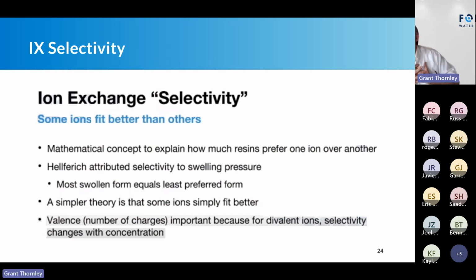It's a mathematical concept to explain how much a resin prefers one ion over another. Again, we have lithium, but we also have lots of other ions in there. So how do we ensure that one ion is going to be selectively removed from another? Helfferich attributed selectivity to the swelling pressure of the beads. That's maybe a difficult concept to wrap your head around, but there is a finesse to that. As the bead loads, it swells and creates a pressure. So the more pressure we have, the less that it can load onto.